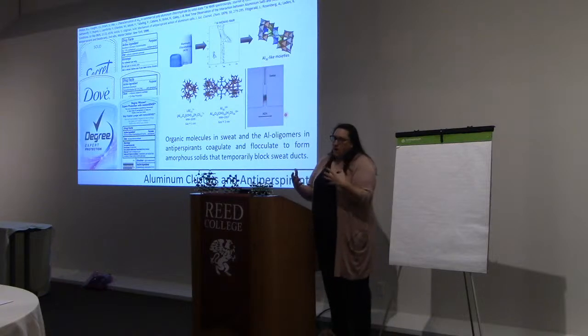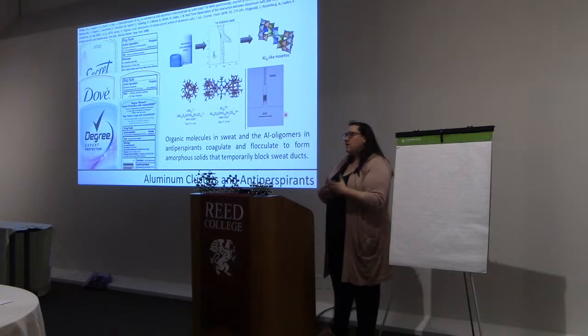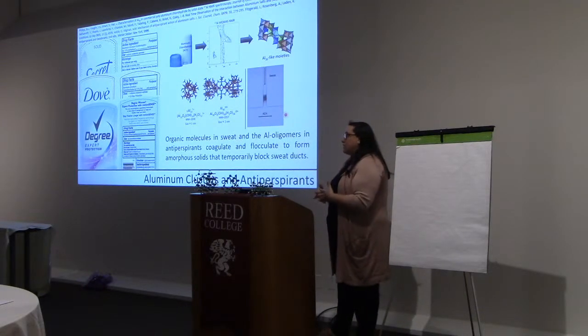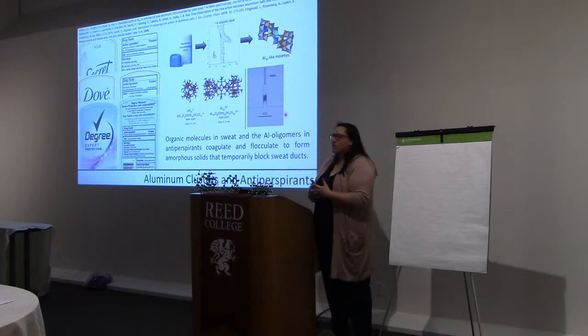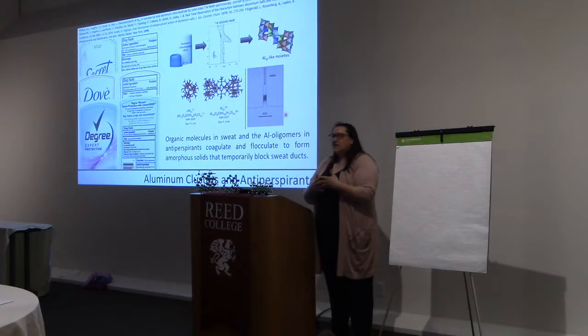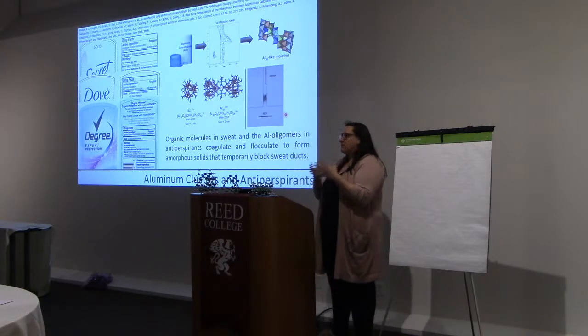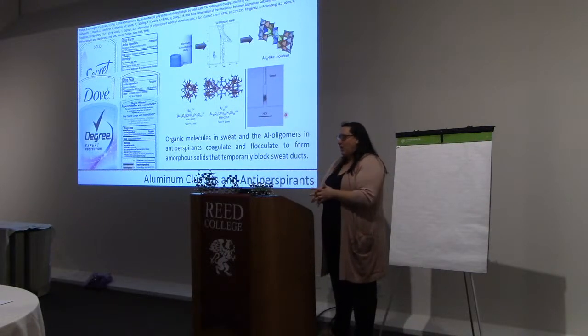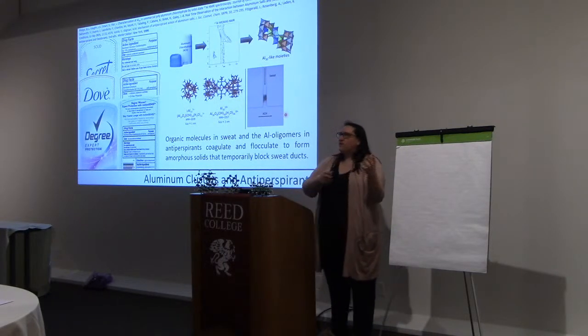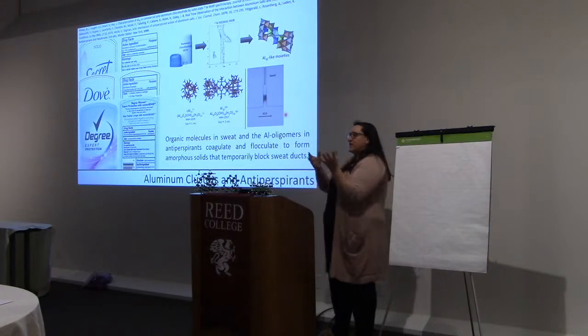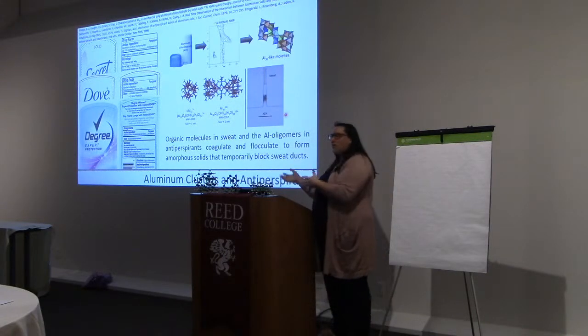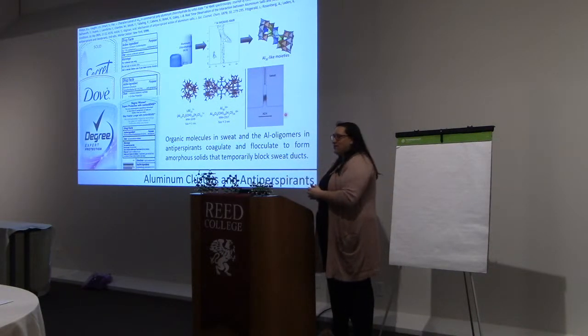So you put the antiperspirant on, the aluminum dissolves into your sweat, it gets into your pores, which are slightly more basic than your sweat might be, and then all of a sudden it precipitates, clogs your pore, and you can't sweat, right? So that's how that's working. And again, as we're going from something dissolved in solution to something precipitating out to clog your pore, we're most likely having those nanoclusters in there.